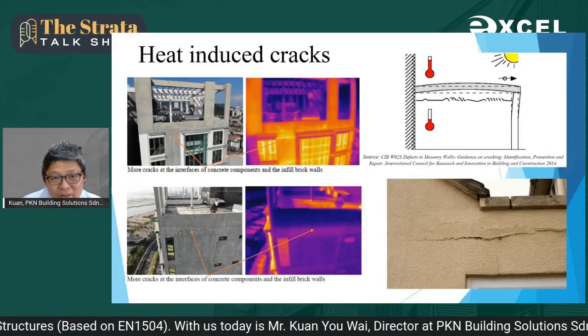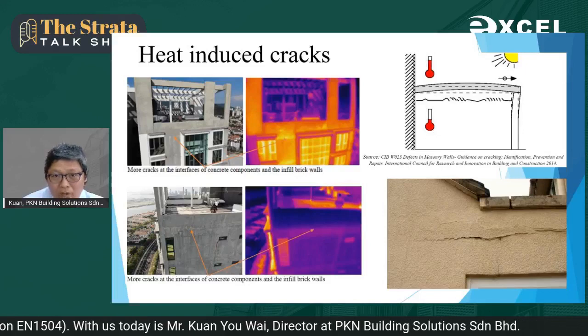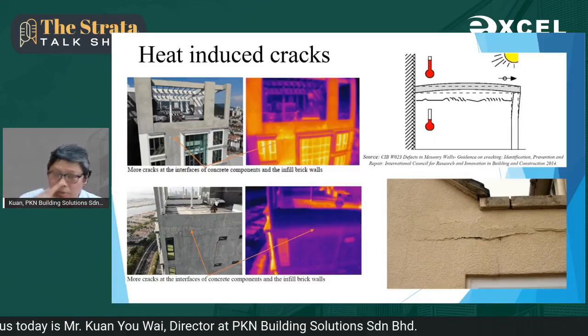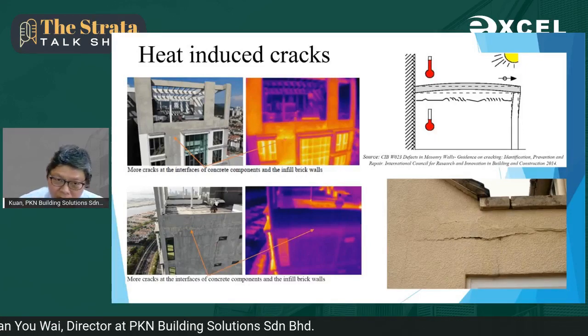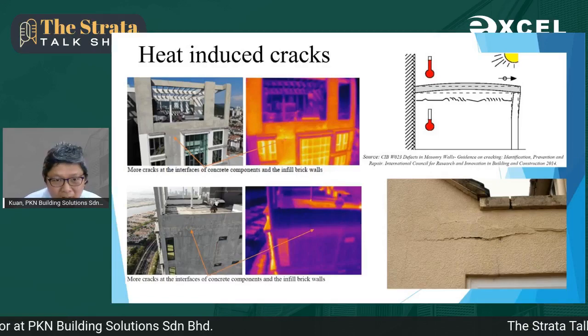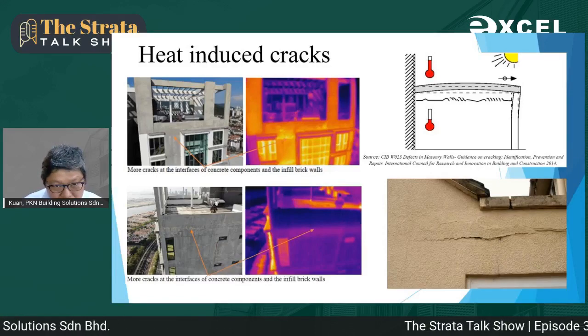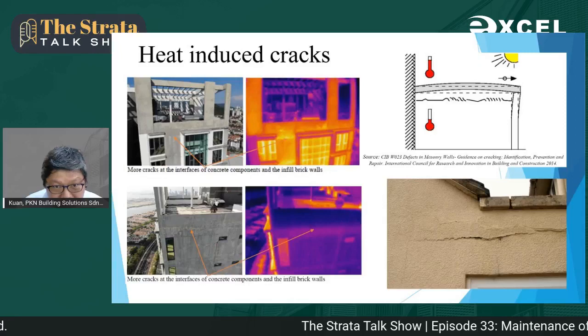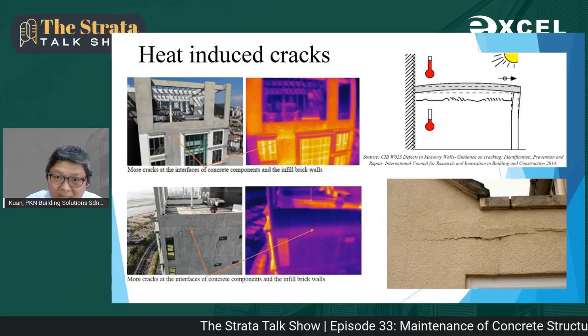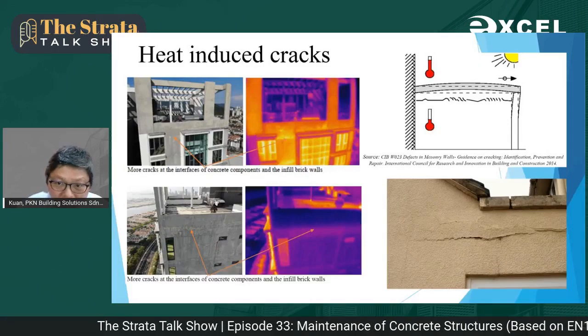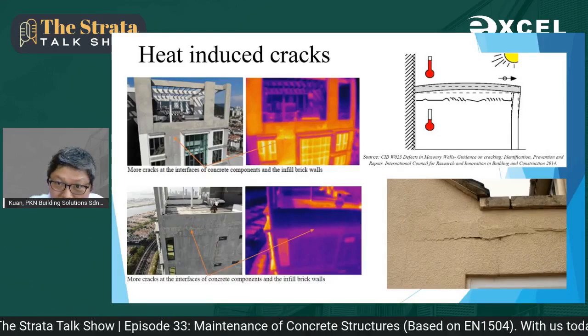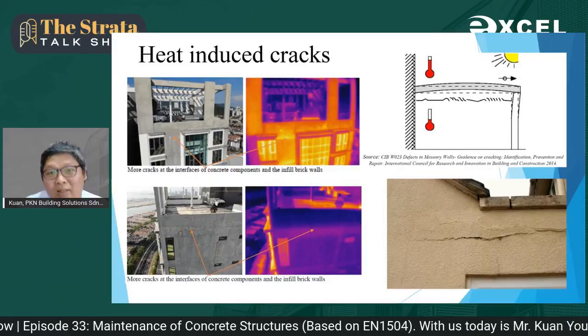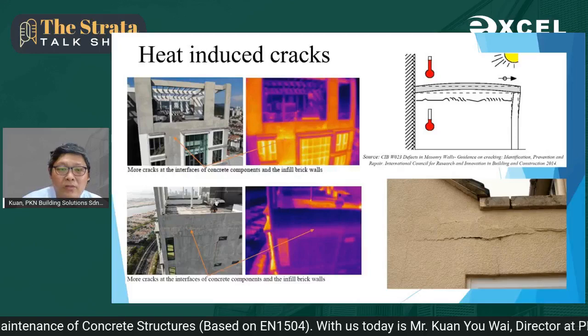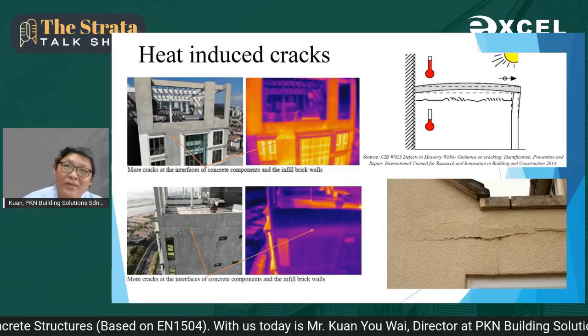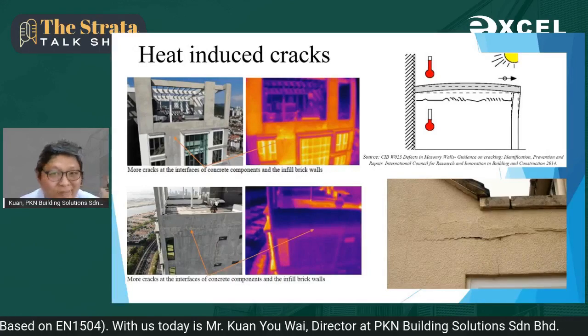And this is actually the mechanism, the horizontal, upon the exposure to the heat, the horizontal flat roof expands. And in this photo, we can see the slab is being heated up. When it is heated, it will expand and it will cause a lot of crack at this part of the vertical wall right under the flat roof. So in fact, it expands and contracts every day.